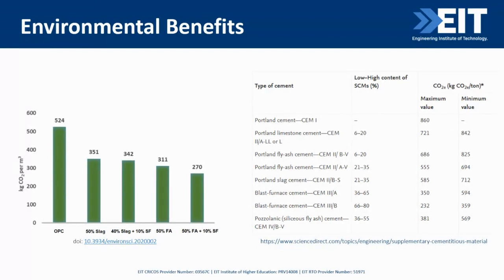In general, for every ton of clinker replaced by supplementary cementitious materials, carbon dioxide emissions are reduced by approximately 0.8 ton. And as we can see from the figure on the left, with a supplementary cementitious materials replacement ratio of about 50 to 60%, the embodied carbon dioxide reduction compared to OPC ranged from about 30% to almost 50%, which is very, very significant. So these are mixtures with supplementary cementitious materials, and this is OPC, ordinary Portland cement.